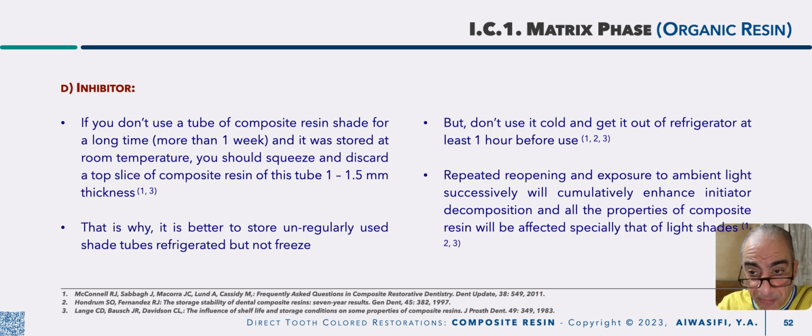If you have a tube which is not commonly used for a long time, it should be refrigerated, not frozen. Why refrigerated? To inhibit the self-decomposition effect. And when you would like to use it, get it out of the refrigerator about 1 hour before, just to become at room temperature.